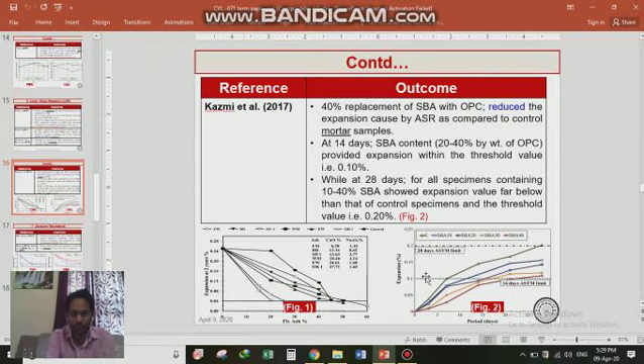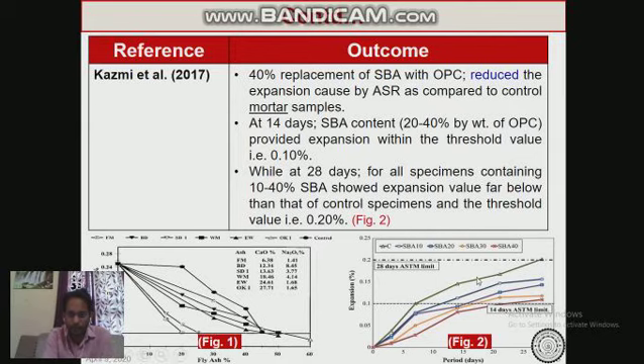Here we can see in figure 2, this is the control sample, this is 10%, 20, 30, 40%, and they have studied at 14 days, where the 14 day limit is 0.1 percentage, and 28 days, where the ASTM limit was 0.2 percentage. It was concluded that at 14 days, SBA contained 20 to 40% by weight of OPC, and the expansion was within the threshold limit.